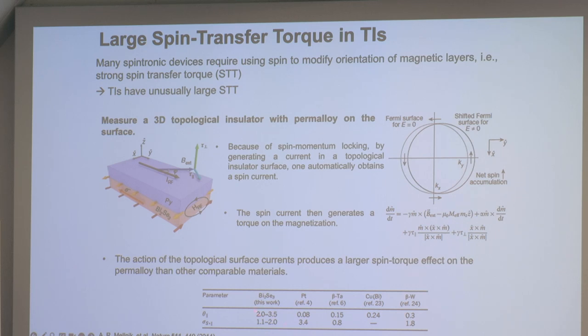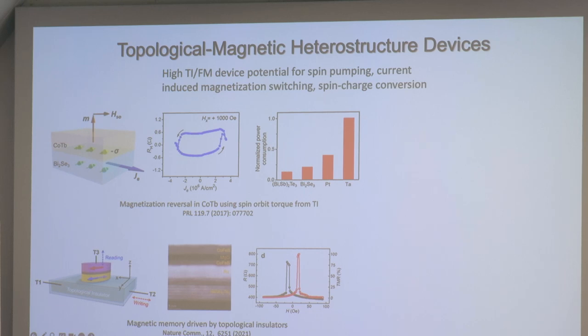And you can see this in just the spin conductivity, for example. This is the bismuth selenide. It's comparable to platinum. It's a little bit smaller. But then if you look at the spin torque ratio, which gives you the amount of spin torque per unit of current applied, you want to have more spin torque with lower current applied. Then you can see bismuth selenide is much, much larger than platinum, tantalum, or many other materials. So it applies a large torque, but more importantly, it applies a large torque with a small charge current. And so this has been shown to be effective in different systems.